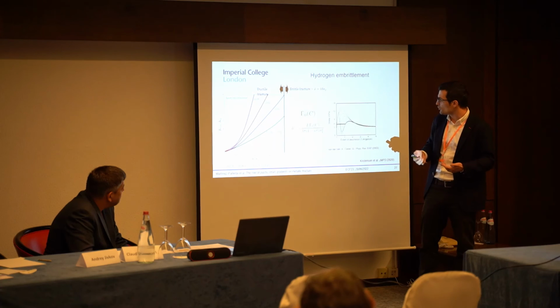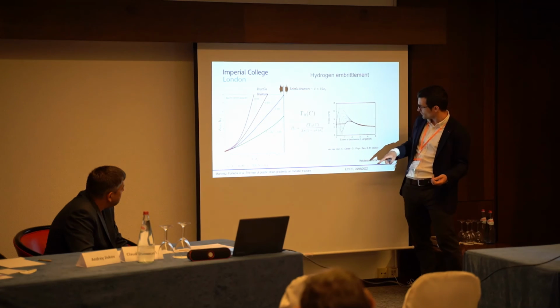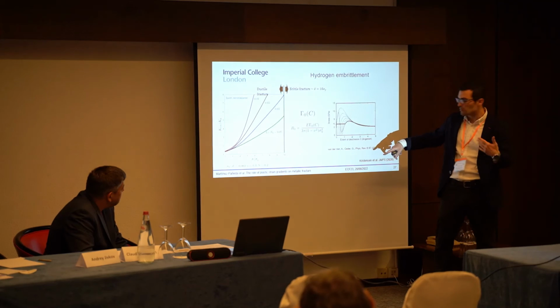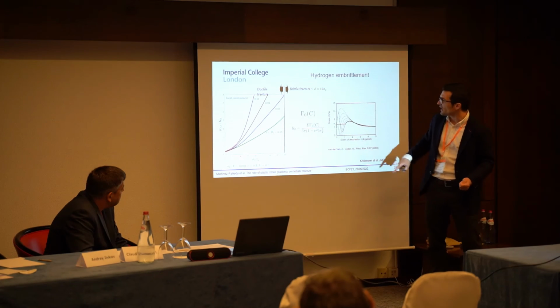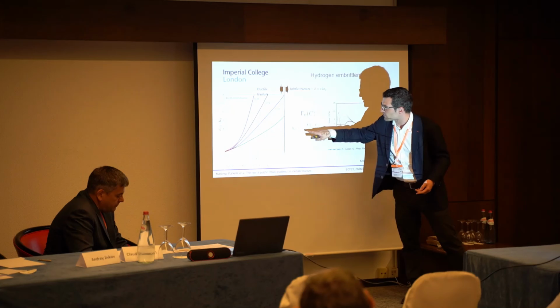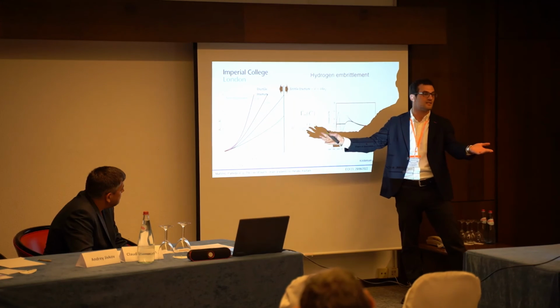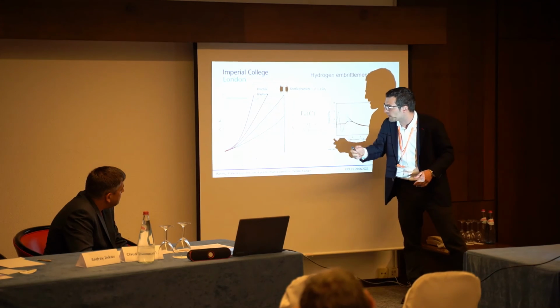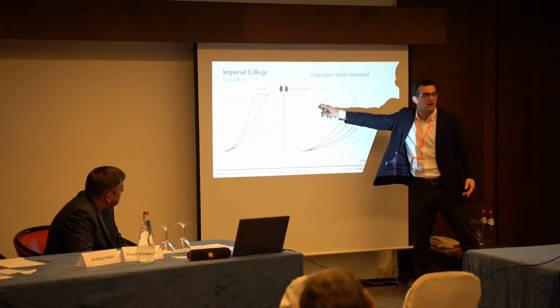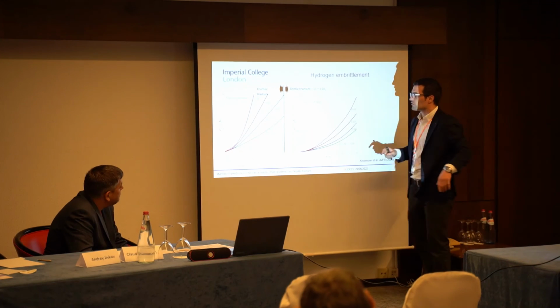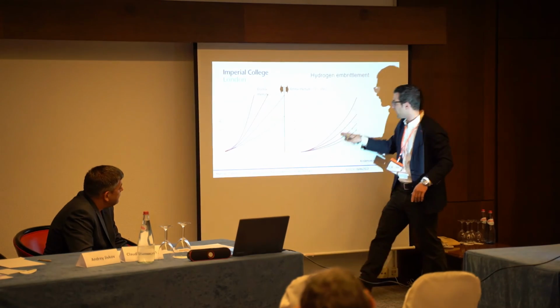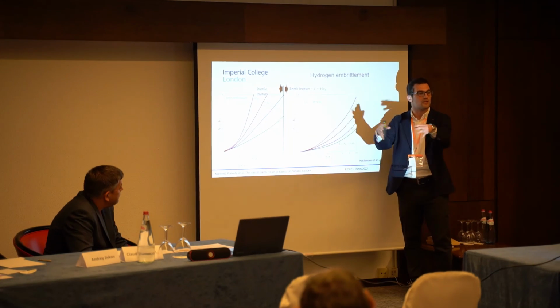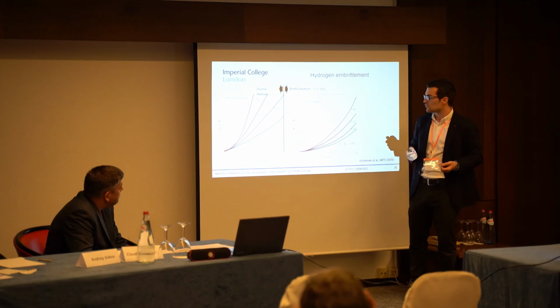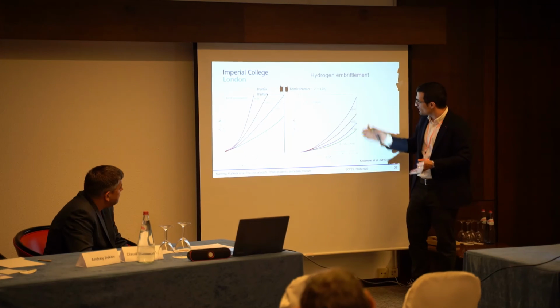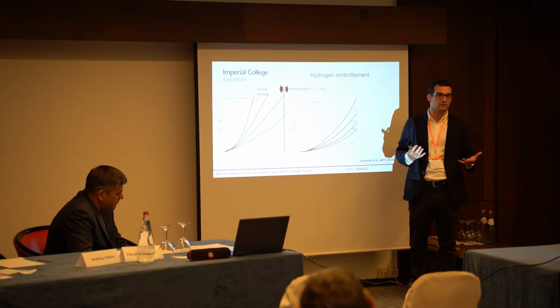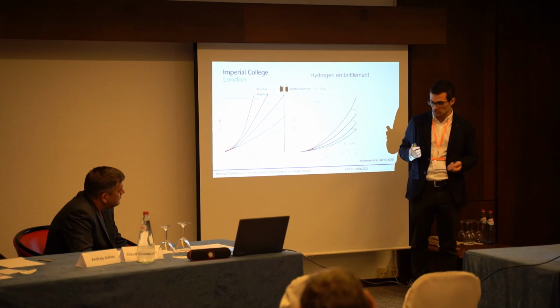But the moment you bring hydrogen into the picture, as they see in the atomistics, these are traction separation laws as computed from atomistics, you can see that there's a dependency on the hydrogen concentration, and you bring down this fracture energy. So you're bringing down your R0. Your L remains the same, it's a material property, but your R0 goes down. And when you take that into account, you put 1 ppm of hydrogen, you see that all these curves shift. So that ductile metal that was lying here now lies here, because you have a much smaller plastic zone, a much smaller fracture process zone size, and you have a much higher stress elevation due to these GND mechanisms. So this, in my opinion, provides a modern interpretation of the cohesion arguments in the context of hydrogen embrittlement.